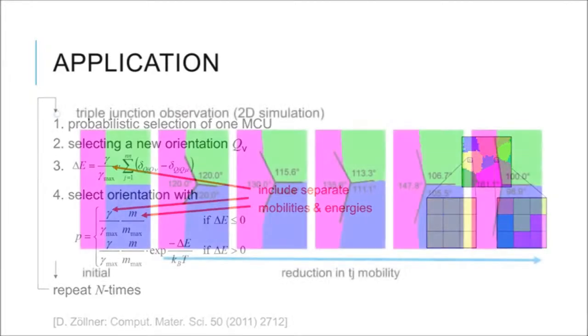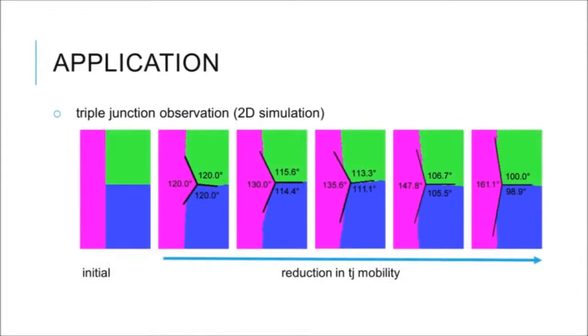Let's take this simulation algorithm and apply it. First, a simple 2D simulation for this scheme. On the left-hand side we have the initial structure, basically just 3 grains, and we take pictures from the quasi-stationary state of coarsening. In the first image of the simulation we have normal grain growth, where the mobility of the triple junctions equals the mobility of the grain boundaries, and we get the 120 degree angles we expected.